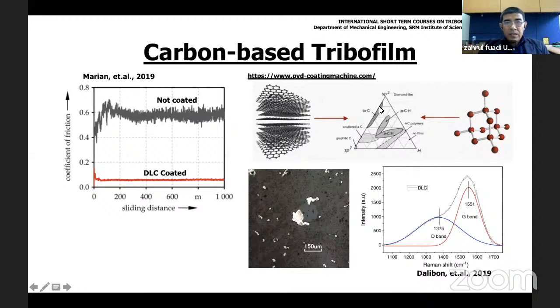And this carbon structure has a lamellar structure like this. So it has a low van der Waals binding force, so it easily slides among each other. So this is an example of steel lubricated by DLC coating. And we can see here that the sliding wear occurred between the coating and the mating surface.